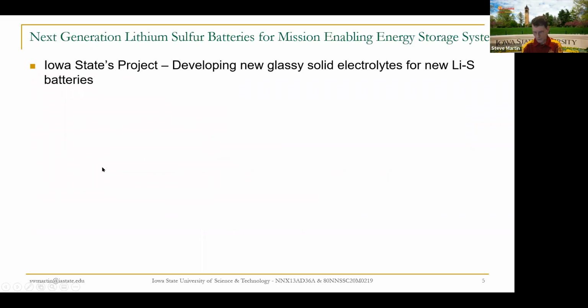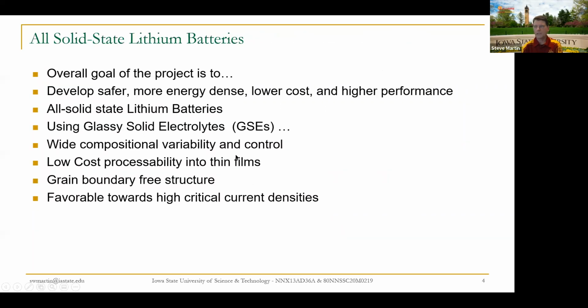I won't go into the details of it, but glasses don't have grain boundaries. They're homogeneous frozen liquids, so they're continuous. There's a detail about how the dendrites grow in the material, and one model has them growing along the grain boundaries in polycrystalline ceramics. We don't have those, so our materials are more dendrite resistant than other types of materials. What that does for you, they're more favorable towards high critical current densities.